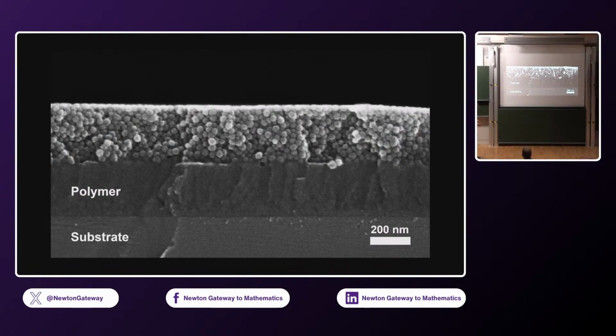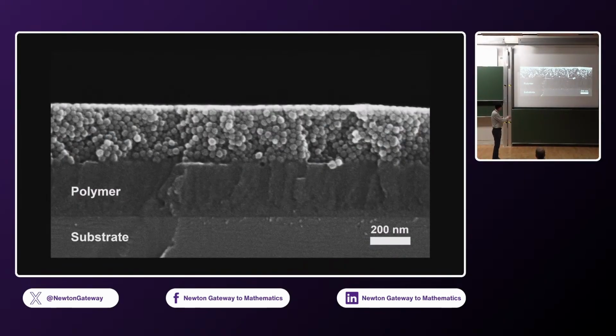Okay, this is what I showed you on my title slide. So this is a substrate, and then I have a polymer layer here. Okay, it's a glassy polymer, in this case polystyrene. On top of that, we spin coat nanoparticles from aqueous suspension. So these were, I believe, 20 nanometer, 30 nanometer titanium nanoparticles. Okay? And then we do one of two things, very simple.